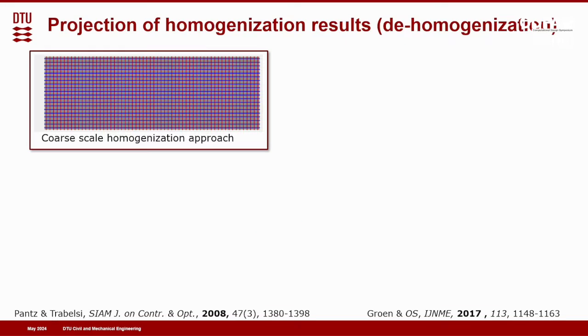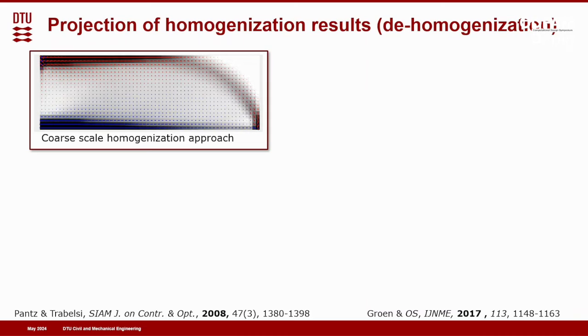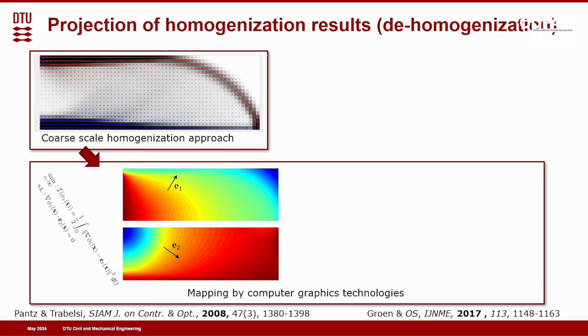So what do we do here? Well, for the dehomogenization, we do exactly what Bendsøe and Kikuchi did 35 years ago. So we have a coarse scale. We do a local optimization with 3 variables for this one load case problem, so the orientation and the lamination thicknesses. It gives us this mushy looking picture here. But then we have an intermediate step where we introduce 2 auxiliary fields with the special properties that their gradient at any point corresponds to the direction of the composites from the homogenization solution. And so this is a least squares problem we have to solve.